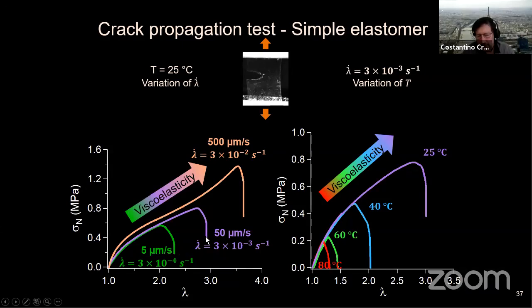And you can see that as you increase the stretch rate, you have a clear increase in the point where the fracture starts to propagate. You can also see that if you keep the stretch rate constant, but you change the temperature from 25 degrees here to 80, the point where the crack starts to propagate changes dramatically. And the material, one would say, becomes more and more brittle as you increase the temperature. This is a well-known result. We just reproduce results that have been obtained in the literature for all kinds of elastomers. So it's nothing surprising there. But now, of course, we have our tool to detect bond scission.